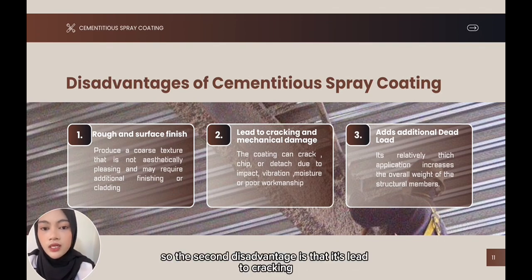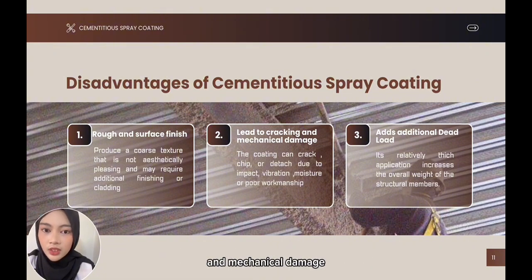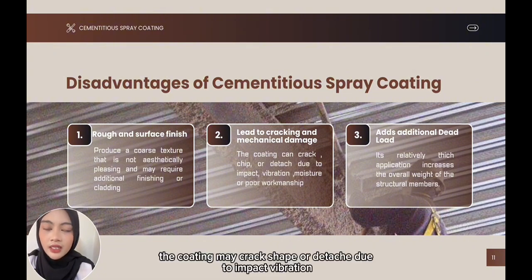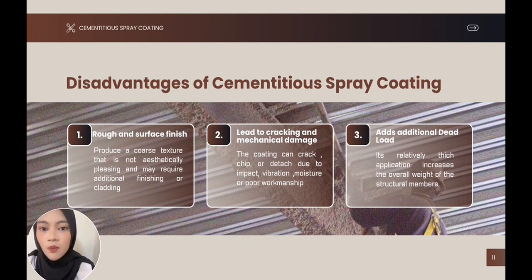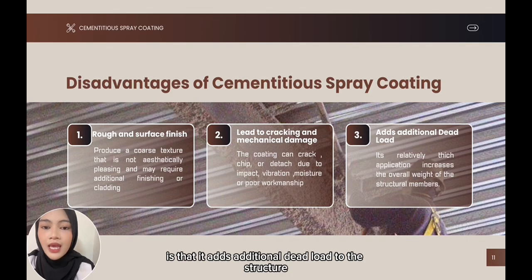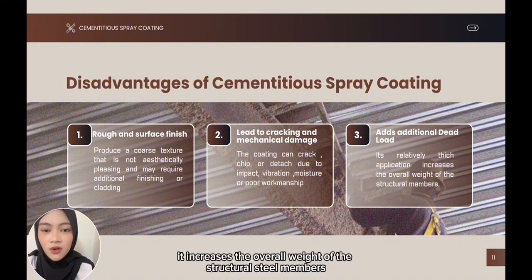So the second disadvantage is that it is prone to cracking and mechanical damage. The coating may crack, chip, or detach due to impact, vibration, moisture, or poor workmanship, which can reduce its fire protection performance. Another disadvantage is that it adds additional dead load to the structure. Since the coating is applied in relatively thick layers, it increases the overall weight of the structural steel members.